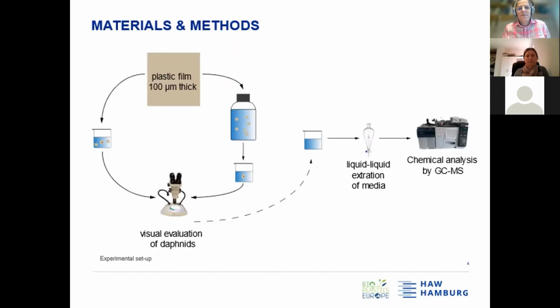After the tests ended, we also evaluated the size and the color of the daphnids, because if they are very small or the color is very light, this is an indicator for bad environmental conditions for the daphnids. Therefore we observed every daphnid by light microscopy with a magnification of 200.